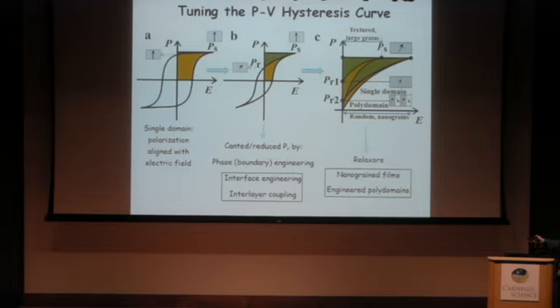You can see here's an example. If you have a single domain to start with, of course, you can change it substantially by applying a field. The characteristic of this loop is that it is very easy to saturate, but very difficult to discharge, right? It's difficult to make the remnant polarization disappear.